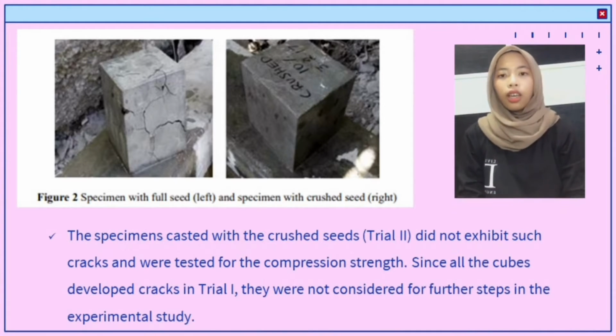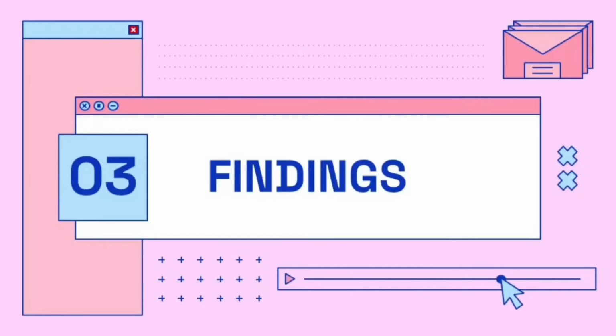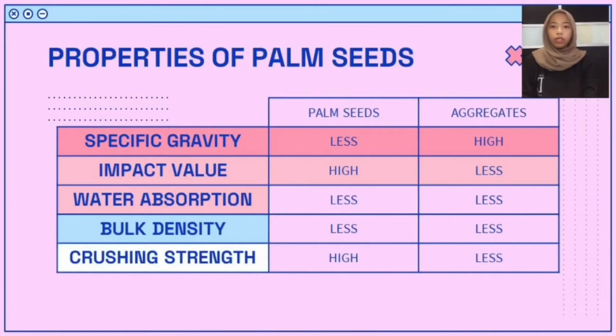As we can see in the picture, the left one is the specimen with full seed, and the right picture is the specimen with crushed seed. The specimen casted with the crushed seed, which is trial 2, did not exhibit such cracks and was tested for the compression strength. Since all the cubes developed cracks in trial 1, they were not considered for further steps in the experimental study.